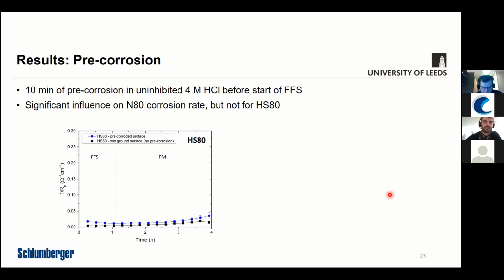So as a comparison, on the left, we're again comparing at the 0.01 weight percent staged test. So we've got 0.2 weight percent during the film forming stage again, and 0.01 weight percent during the film maintenance stage for the following 3 hours. And you can see, for the black line, this was the wet ground surface, so there's no pre-corrosion.